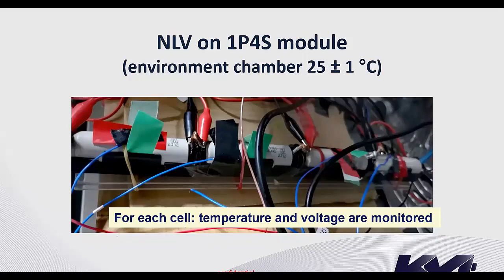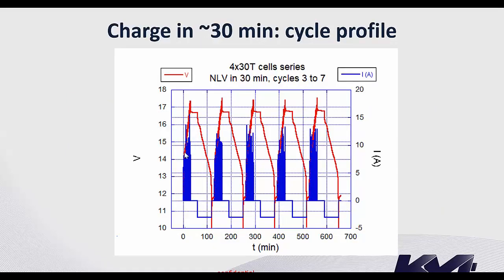So this is just one example where we put 4 cells in series. This module is called 1P, 1 parallel, and 4S, 4 series, okay? In this case we charge it in 30 minutes. And you can see here that the voltage can go to about 17.5 volts, okay, and the current can go to about 12 amps, okay, in this case up to 4 amps, and we were able to do many cycles like this. We did 400 cycles without losing capacity of the battery module, which has 4 cells in series.